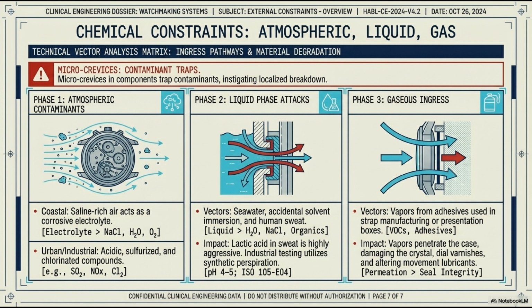If you live on the coast, the saline-rich air acts as a corrosive electrolyte. If you live in an urban environment, the air is full of acidic, sulfurized, and chlorinated compounds from exhaust and industry. Phase 2 is liquid phase attacks. The primary vector here is not seawater, it is human sweat. Sweat contains lactic acid and salt. It is highly aggressive. In the lab, we actually test cases by soaking them in synthetic perspiration with a pH of 4 to 5, governed by ISO 105E04.